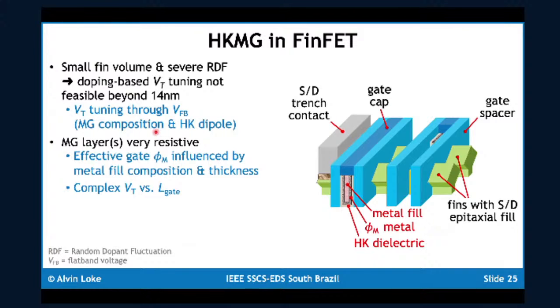The metal gate layers are very resistive, which means that the charge in your gate is not all contained in the metal gate layer. In other words, your Debye length of your gate charge is essentially thicker than the metal gate layer itself, which means that some of it spills into the metal fill, meaning that the effective gate work function is influenced also by the metal fill material as well as its thickness.